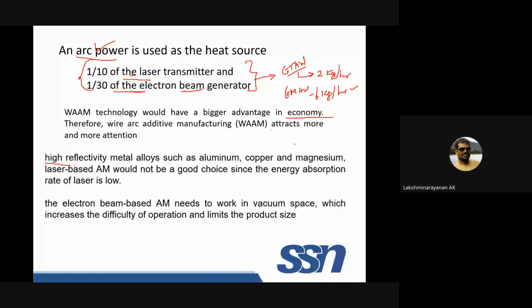There are other advantages. There are problems with laser-based additive manufacturing, especially when you want to fabricate components from aluminum, copper, and magnesium, which are highly reflective. In laser melting, your metal needs to absorb the laser. Since aluminum, copper, and magnesium have highly reflective surfaces, laser is not a good choice. The absorption is less. As I told, the efficiency is very low. Only 20% or 30% of the laser energy will be used to melt the material. All the rest will be radiation or heat loss, because of the poor absorption.